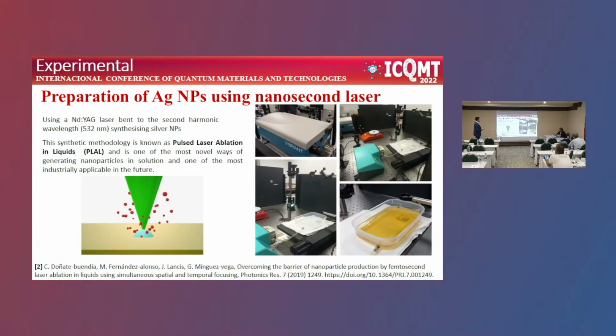Well, how can I produce these silver nanoparticles? The most industrially applicable method, from my point of view, is using the nanosecond laser. What is this technique? It's pulsed laser ablation in liquids, where we apply the laser onto a metal substrate, and with the pulses of the laser we ablate the material. In this case, we produce silver nanoparticles, whose colloid color is yellow.